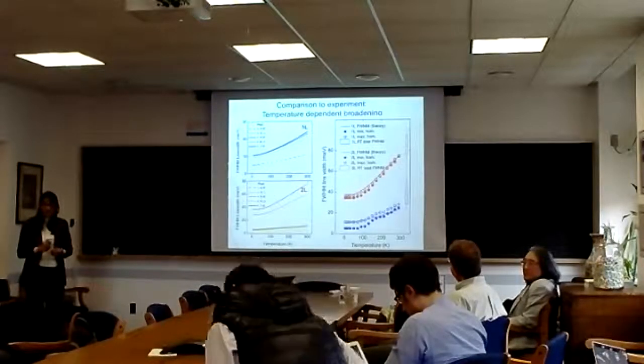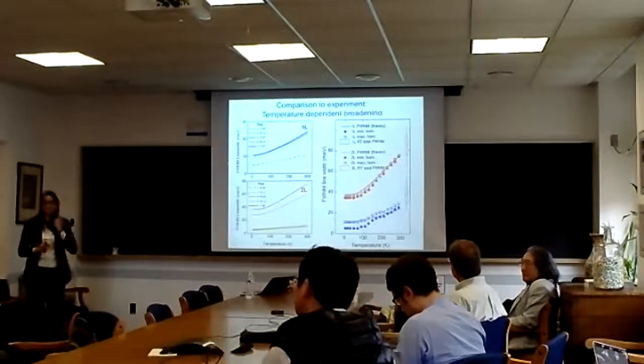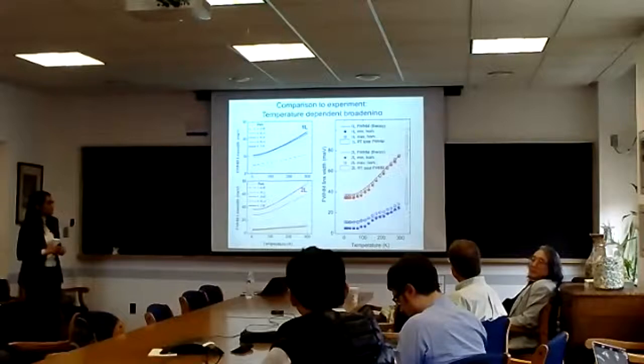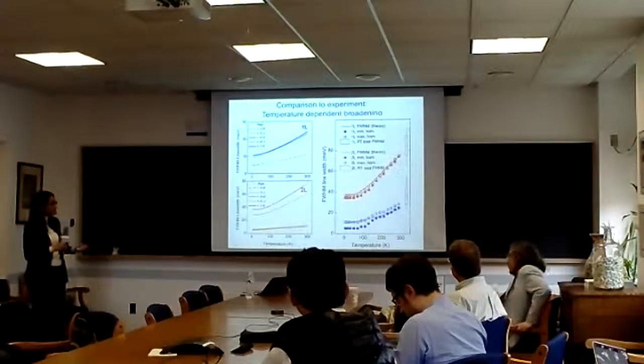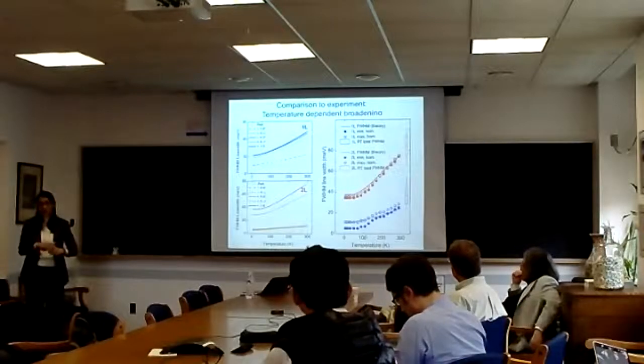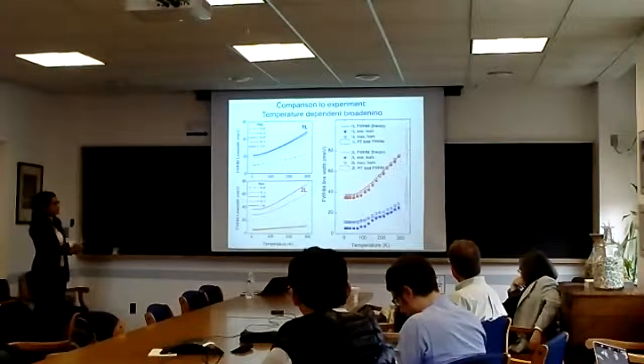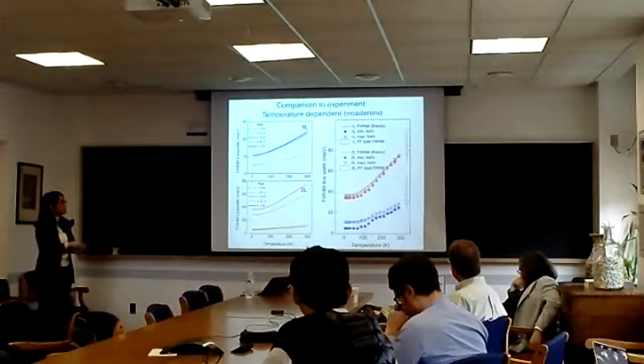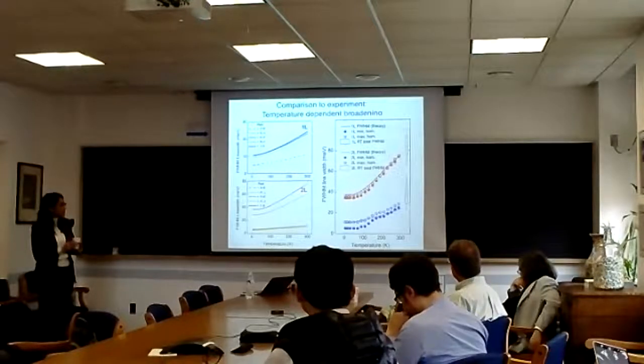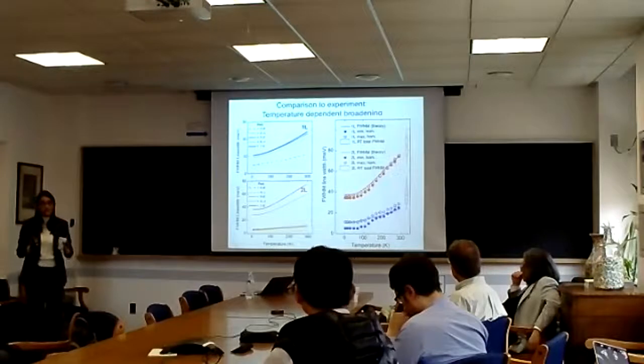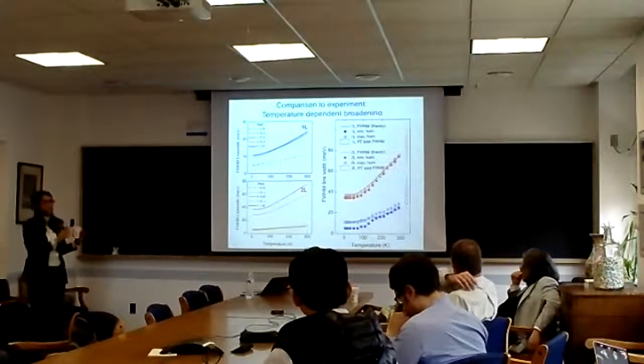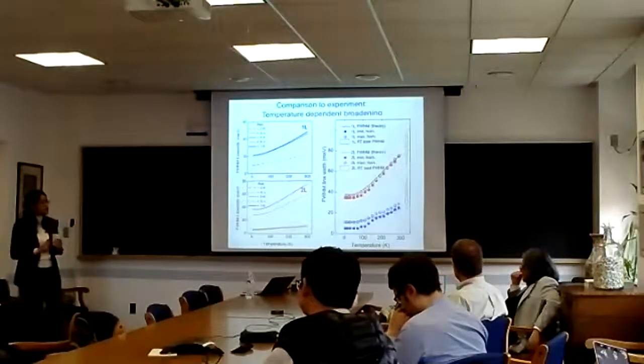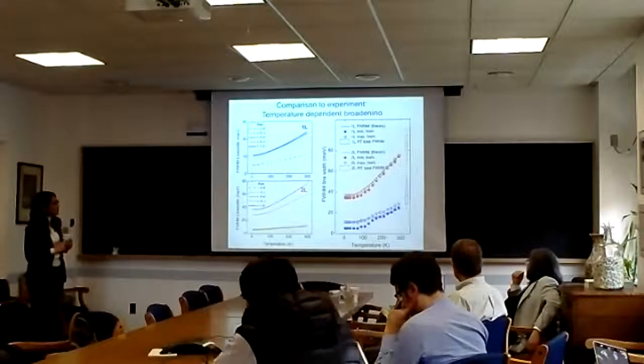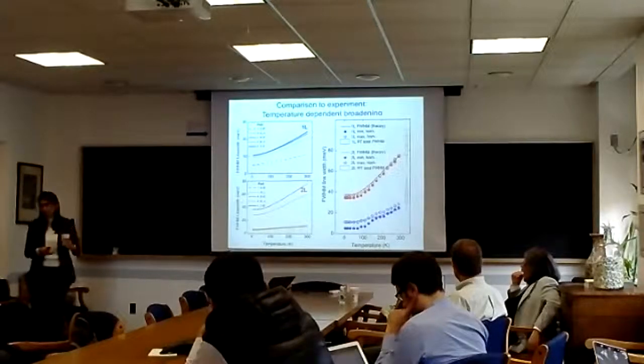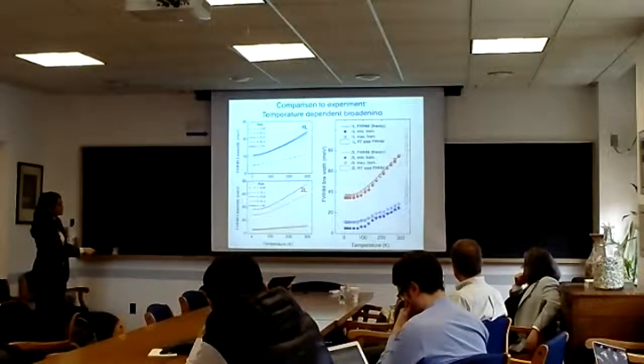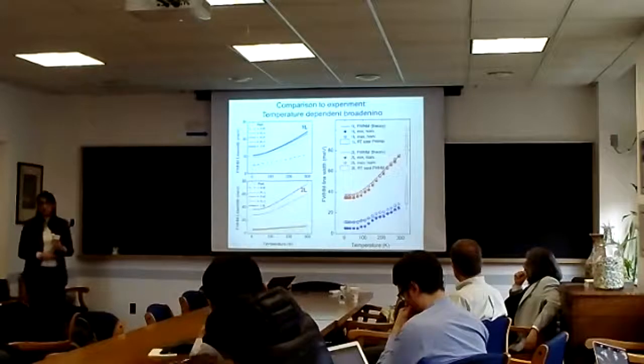They have the same reflection symmetry, right? Mm-hmm. So the way we want to take this next is to look at, as a function of angle, how these line widths are being tuned, because not all of these will be active then. Not these very magic small angles, but just a way to tune line widths itself. And I think the natural bilayer system is just the starting point of understanding what's going on. Initially we were convinced that this was all due to just the indirect gaps, but it turned out that's actually just 1/5 of the contribution, so to speak.